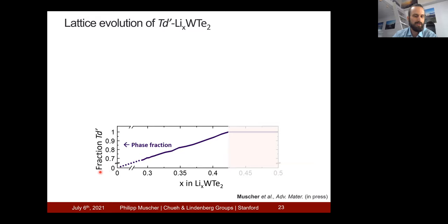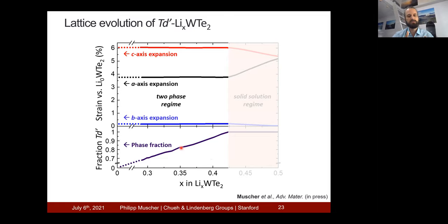So then I can plot the fraction of the new phase as a function of the overall volume of the flake as we're inserting more and more lithium into the material. You can see that the phase fraction is increasing linearly until we reach a composition where the X in this formula is 0.42. At that point, the whole sample is in the new TD prime phase. And then by looking at the positions of the reflections, we can also learn about the unit cell parameters of the sample.